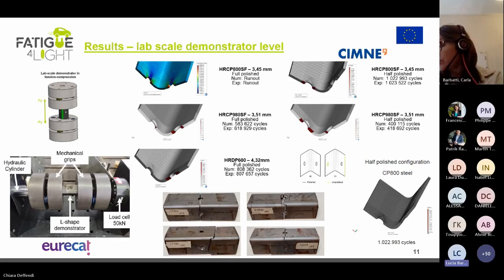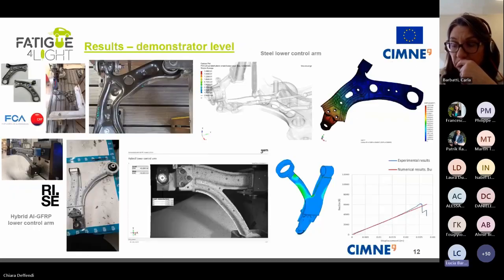From CIMNE's side, from my institution, we performed a numerical analysis campaign. And then we saw if with the fatigue numerical approach simulation that we have, we approximate correctly the behavior observed experimentally. And here you can see that we do. There was a small animation here, but unfortunately you will not be able to see it, with the crack propagation at a bit past 1 million cycles for the CP800 steel.